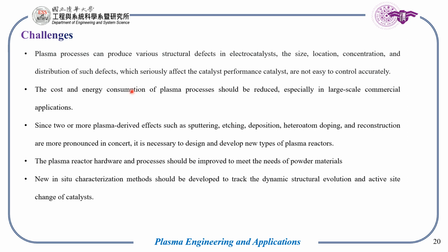The next problem is that plasma technologies involve high cost and energy consumption. And the third point is that since two or more plasma-derived effects, such as sputtering, etching, deposition and heteroatom doping, are more pronounced, it is necessary to design new types of plasma reactors. Two or more plasma technologies could be implemented in a single reactor, and this is one of the challenges being faced. And new in situ characterization methods can be developed to track the dynamic and structural evolution of the active sites and of the changing catalyst. Such new characterization could provide real-time information on how these active sites are created on the electrocatalyst.